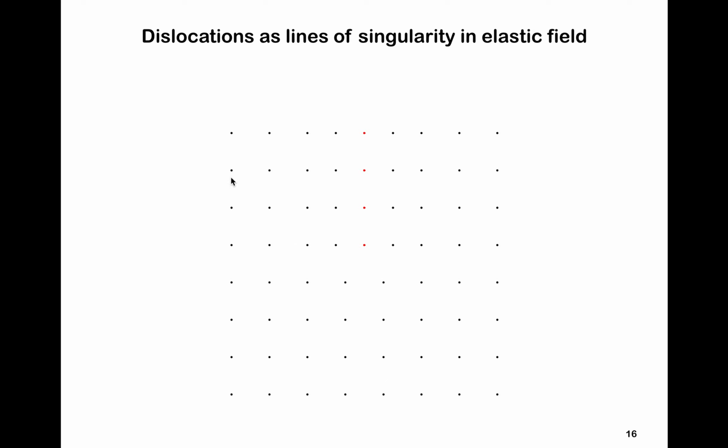If I look at these four atoms, they all form the vertices of a square. Same here, same here, and so on. But if I look at this region, I see a collection of 5 atoms. They do not form the vertices of a square. So this clearly is a change in the local geometry, and that is a telltale sign of a dislocation. This extra layer shown in red should not be present. It is extraneous to the system, and this is an example of an edge dislocation in a cubic crystal.